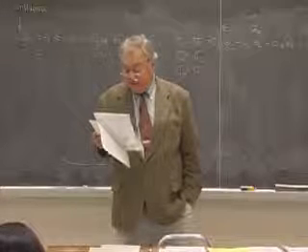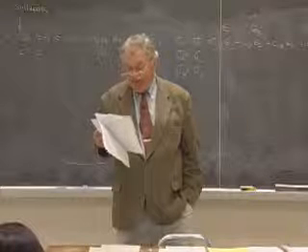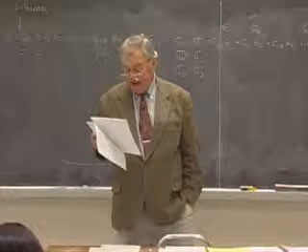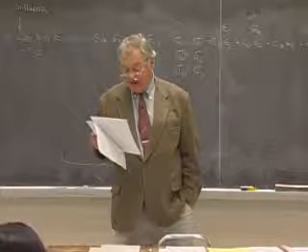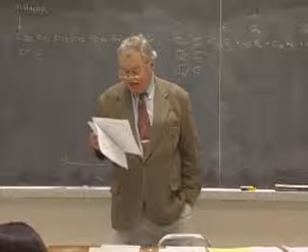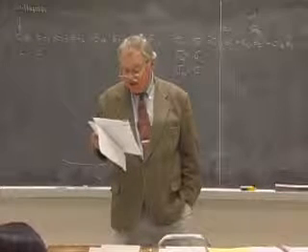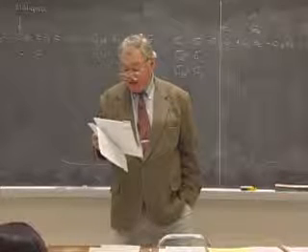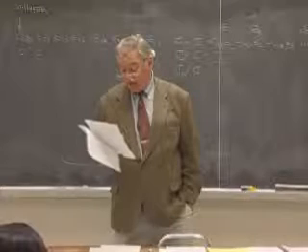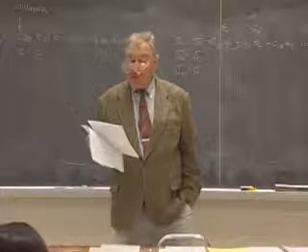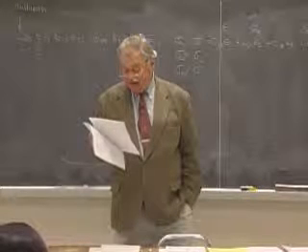In defining the matrix stiffnesses, the C's, you forge straight ahead and you let Cijkl, which is identical to Cijlk, that's the term that relates the two equal shear stresses, and you define that as a matrix term with two subscripts. No factors of 2 or 4 are involved. And then when you hit the S's, there's a nightmare.